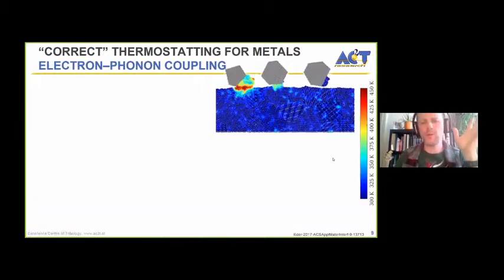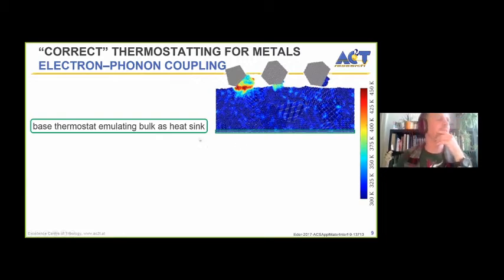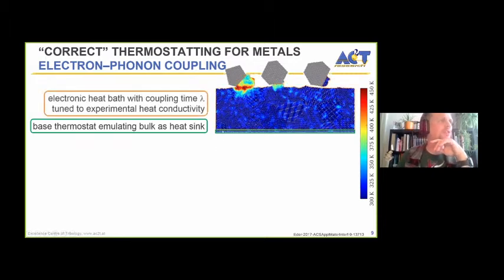So he showed me some old papers of a former colleague of his. And it turns out there's a very simple, straightforward way of doing this. You just have to do it. And that is you emulate the bulk with one heat sink at the very bottom. And then you have a separate parallel heat bath that basically does the electron-phonon coupling. So that couples your electrons to the phonons with a certain coupling constant, coupling time.